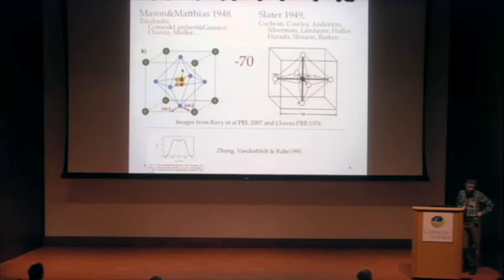But if we think not about Landau theory but about statistical physics, we come easily to understand that it's useful to think about titanium being somehow off-centered, and maybe there are some specific positions, which is the idea of eight-site disorder of titanium. And the real question, which was already clarified quite a lot before, is: what is the dynamics?